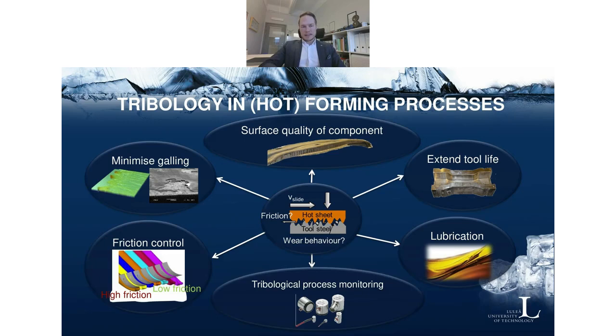Minimizing galling, I will come back to that several times during this talk, but material transfer is a main concern in many processes, especially when we're dealing with high performance materials. And this, of course, has a detrimental effect on, for example, surface quality of the component or tool life. So this is an important aspect that needs to be considered in many processes and from many aspects. Lubrication, likewise, of course, type, amount, and so on and so forth is important. And process monitoring with a connection to tribology is also highly interesting, because the more you can measure and the more information you can extract from a process, the higher the chance of actually being able to detect deviations from the robust process window, and when it starts to deviate and create problems in terms of quality or performance.